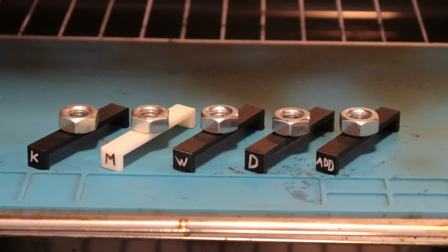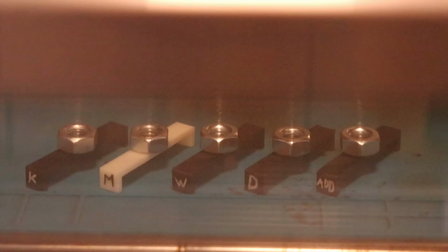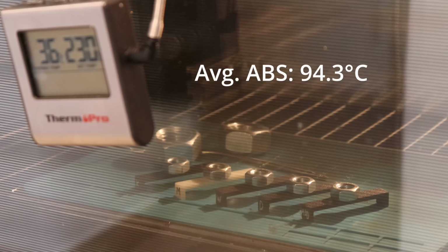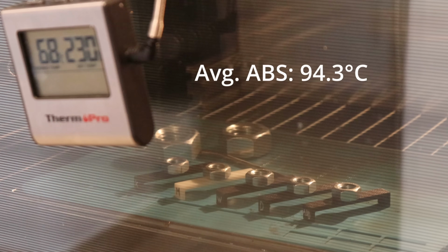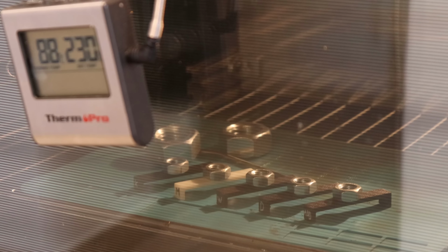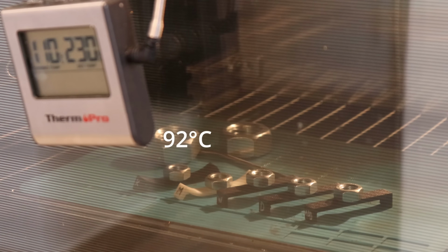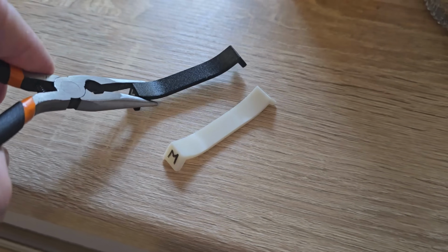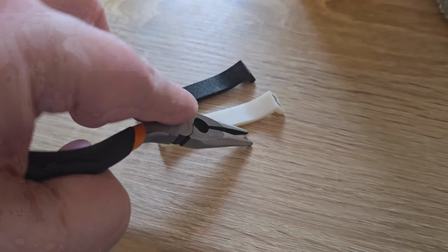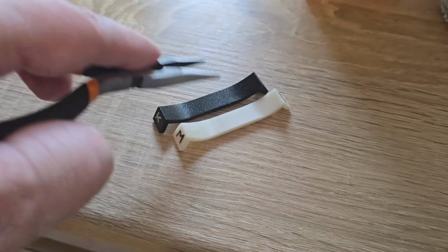Temperature test in the oven. This one is the filament from this video. I have several tests in progress. The average ABS, 94.3 degrees Celsius. And this one was quite close. At approximately 92 degrees Celsius I noticed the first deformation. At 115 degrees Celsius I took it out, but very quickly it became hard and solid.